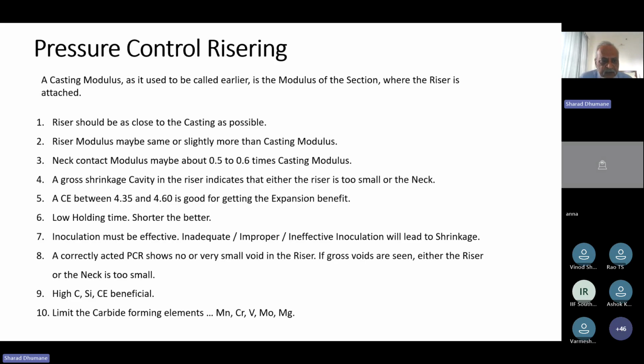Whenever that particular initial metal went, it showed carbides. So I'm just giving my own experience that for inoculation to be effective, it is not only choosing the right inoculant, right size or particle distribution, but how we add the inoculant. My own experience is that if we do inoculation perfectly, no mold stream inoculation is required. If you require mold stream inoculation, that means somewhere in the initial stage something needs correction, something needs your attention, and when you do that, then you get excellent benefit of inoculation, and probably no cases of carbides or other impacts of bad or inadequate inoculation.